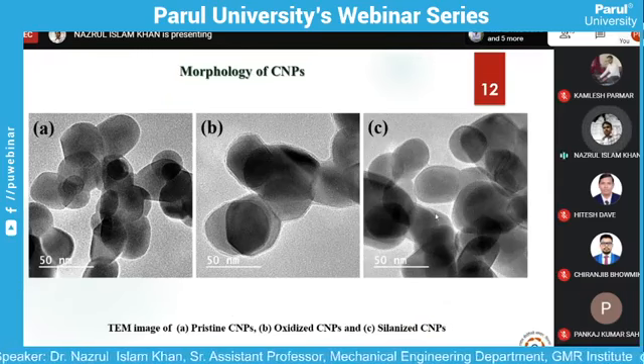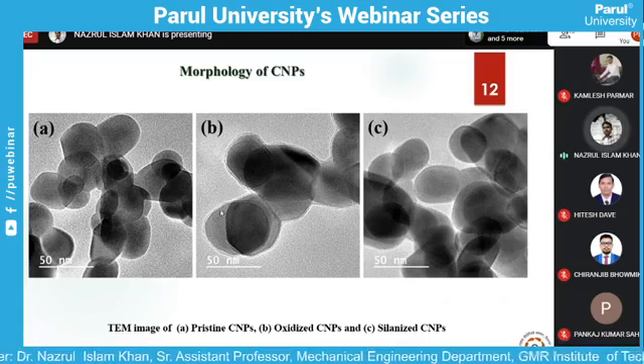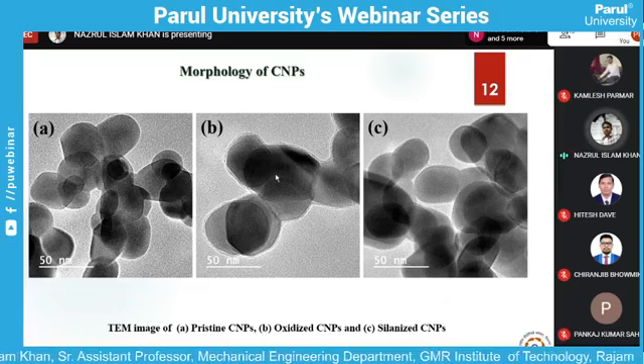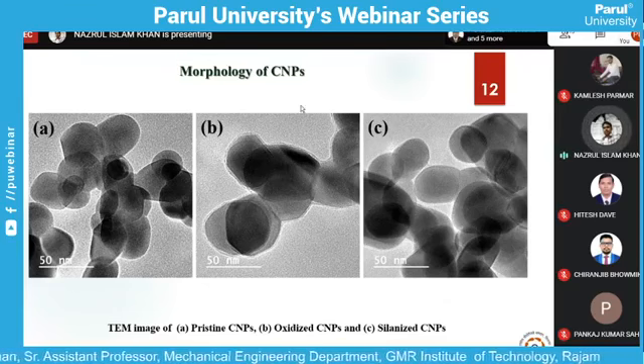And this is again a very simple example from transmission electron microscopy on the surface, where you can see a very uniform layer has been deposited on the surface of graphitic nanoparticles or carbon nanoparticles.